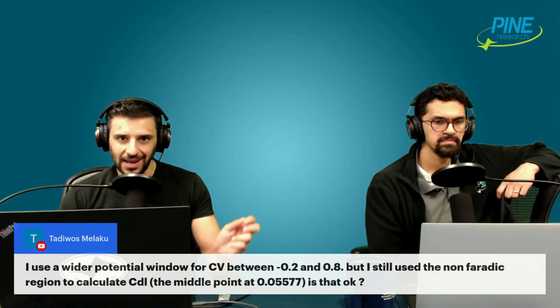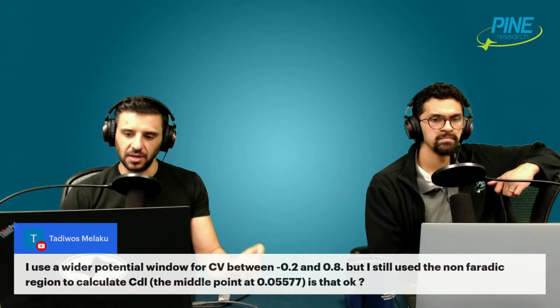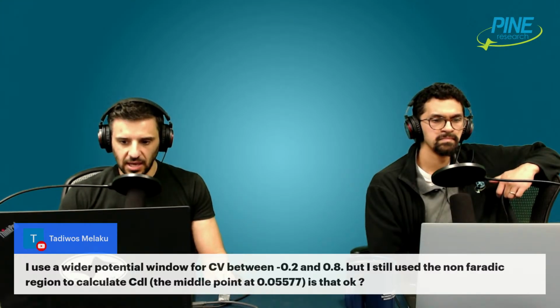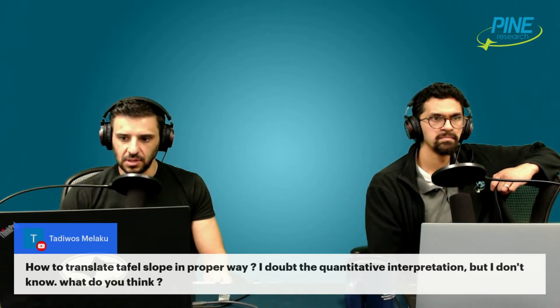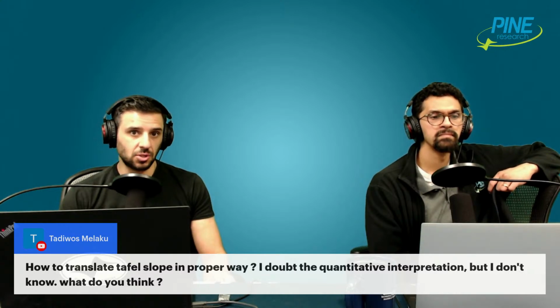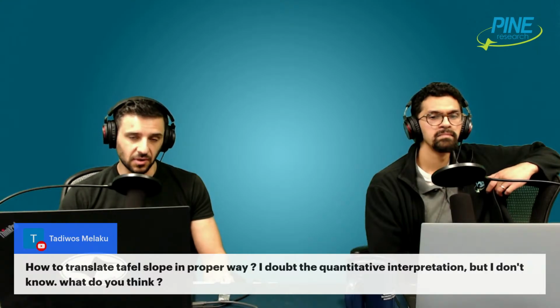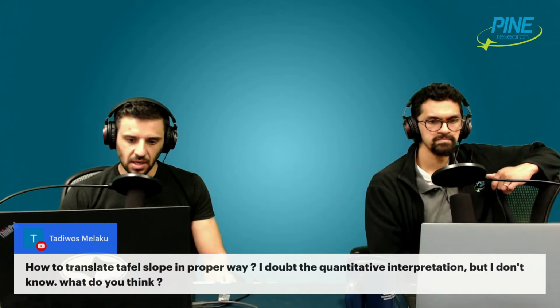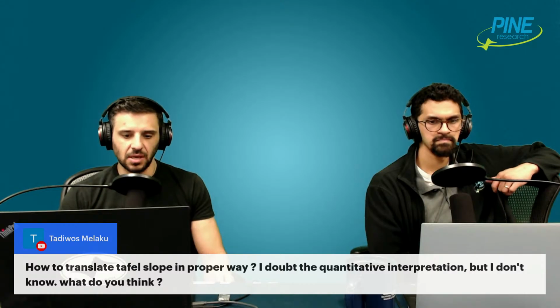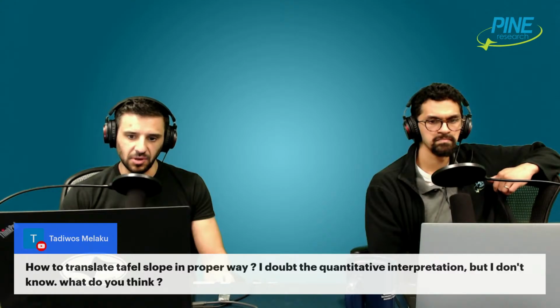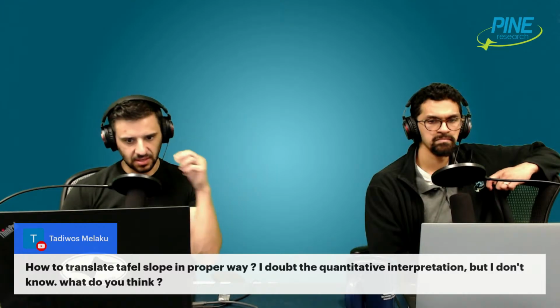The key there is kinetic. It's not current, it's kinetic current. So, to your first comment, how to translate the Tafel slope in a proper way. In some sense, make sure that the Tafel slope that you are measuring is even appropriate in the first place. Because the translation, so to speak, of the Tafel slope depends on whether it's even appropriate to make the Tafel slope at all. Okay, and I'll show you what I mean because I have a slide on this.